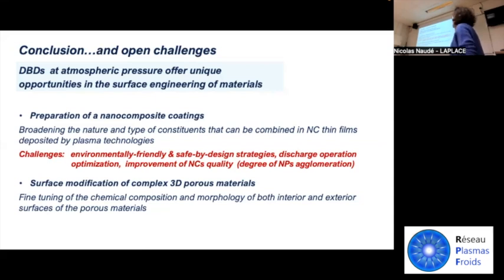As for the surface modification of complex three-dimensional porous materials, it seems that atmospheric plasma offers the possibility of achieving a fine-tuning of the chemical composition and morphology of both the interior and the exterior surfaces of porous materials. Really a fine nanotexturing that is not easily achieved with simple wet chemistry procedures, for instance, or other gas phase techniques in which there is no penetration of plasma.